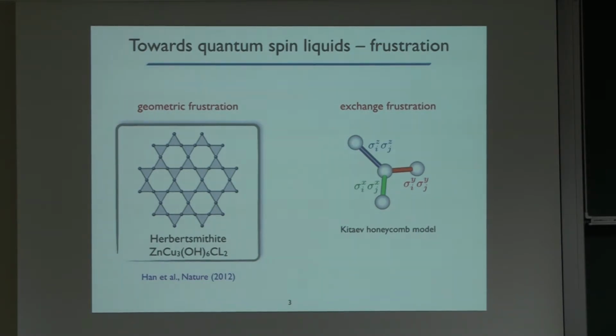Okay, so that is geometric frustration, and it's one of the main driving forces for getting quantum spin liquids. One of our best candidates currently for a quantum spin liquid material is herbertsmithite, where the magnetic sites form this Kagome lattice. On each site you have a spin-1/2 degree of freedom, with Heisenberg interactions. This is really one system where we believe the ground state should be a quantum spin liquid. So this is very interesting, but it's not what I'm going to talk about. I'm going to talk about another way of frustration, which we call exchange frustration.